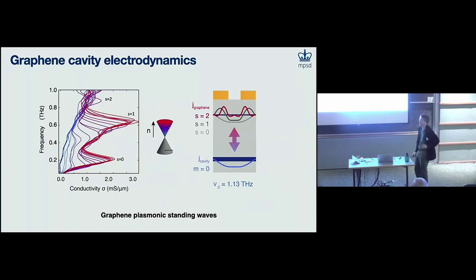Okay. So you showed these nice results with the suppression of the dependence on n. I would imagine you'd see similar suppression in terms of k, the momentum, and therefore slower group velocity. Do you see the pulses going slower through the graphene? The group velocity is heavily suppressed. It's close to the Fermi velocity because it's a very slow plasmon just from the screening environments. That's expected. Now, as a function of k, that's more challenging. We are measuring at finite k. Obviously, they're standing waves. And the momentum of the light in our circuit is basically set by the separation between the waveguides.